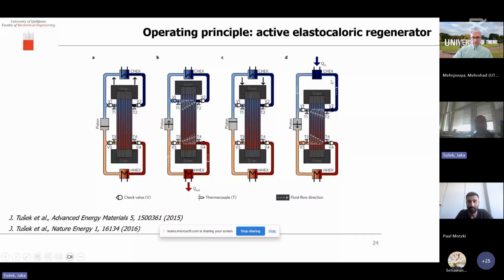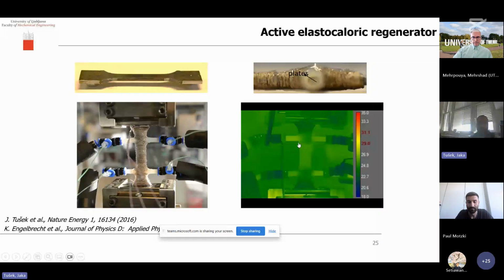So as I said, a couple of years ago, we designed the first such system. Here is the picture, and here is the IR video of the operation. So there are 4 basic operational steps: loading, fluid flow towards hot side, unloading, and fluid flow towards cold side. And we can see that after a certain number of cycles, a temperature profile is getting established along the length, and we can build a temperature span of, in this case, 20 kelvins between cold and hot side.